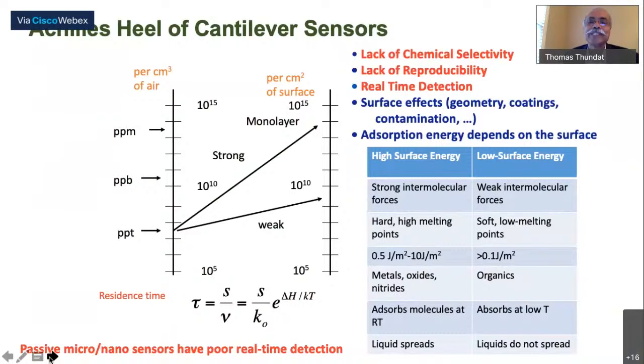First, lack of chemical selectivity. And second one is a lack of reproducibility. And the third one was real-time detection. The lack of chemical selectivity is what I am going to address in this talk. So if you have molecules in air, say parts per million, parts per billion, parts per trillion, and depending on the interaction between this adsorbed molecule and the surface, which we may modify, it can be gold or platinum or some kind of material or silicon.